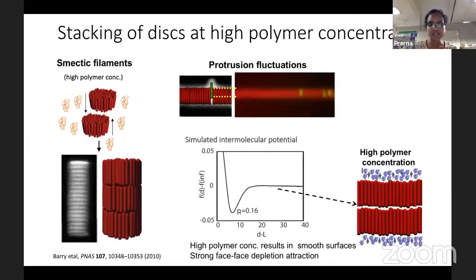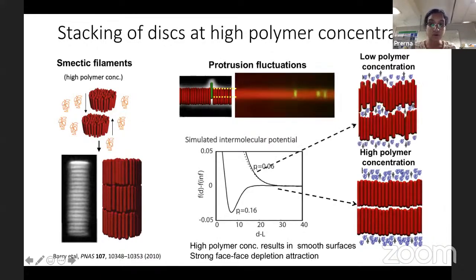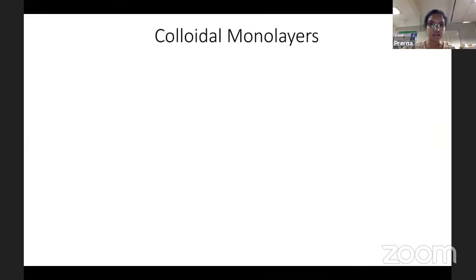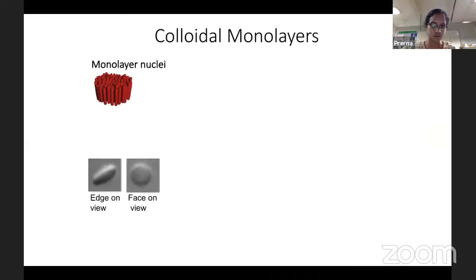You can analyze it to find out that at high osmotic pressure, which means at large polymer concentration, the surface of these discs are very smooth, and so they stack up on top of each other. But at low polymer concentration, you have these significant protrusion fluctuations. Now if you try to bring two sheets on top of each other, you're going to suppress these protrusion fluctuations, which is entropically unfavorable. So you end up with these monolayers of aligned rods.